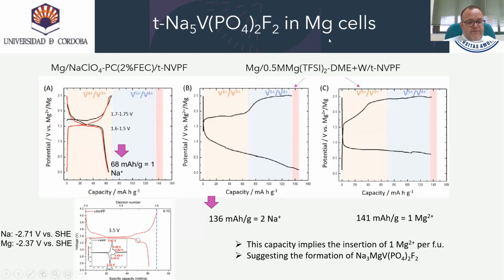The electrochemical performance of trigonal NVPF is tested in a magnesium cell. For comparison, a hybrid cell using sodium electrolyte and magnesium metal anode is displayed. All the cells have been cycled between 2.5 and 0.1 volts versus magnesium under the same conditions.